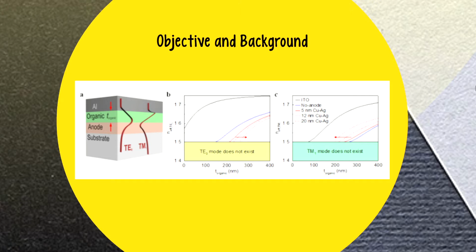The schematic of the OLED shows that waveguide modes TE0 and TM1, which are the two lowest-order modes, are typically guided in traditional ITO-based devices. This is because ITO has the highest refractive index of all layers. In contrast, low-loss metals such as Ag have a real part of the refractive index close to 0, and therefore can drastically reduce the effective index of the waveguide layer.